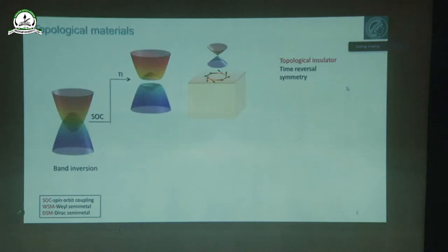Due to the inversion of the band gap, we have a surface state on the surface. This surface state is very robust and metallic, but not a normal metal: the spin and momentum are locked together. This is called a Dirac band, linearly dispersed, where the electrons move very fast. For that we have to preserve the time reversal symmetry of the band. So basically, a topological insulator is insulating in the interior of the band, and outside,